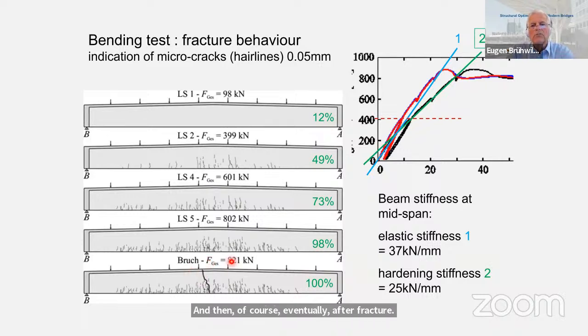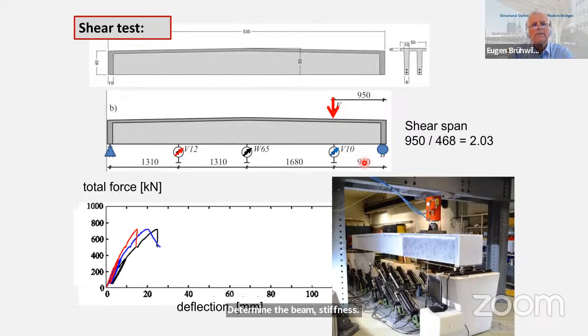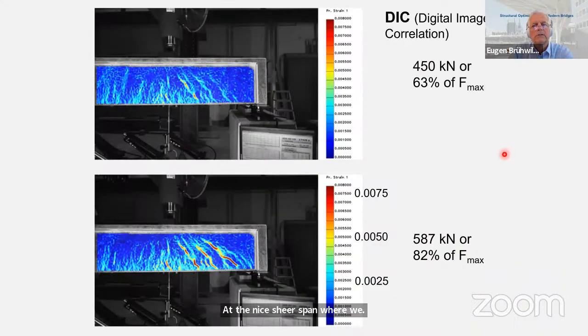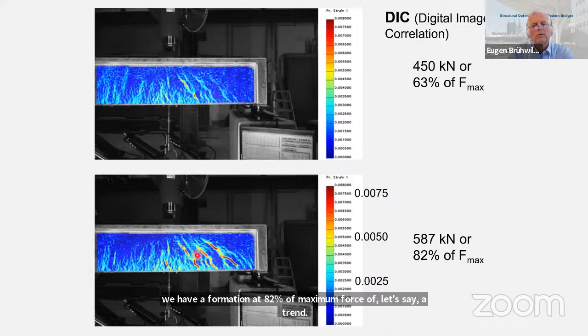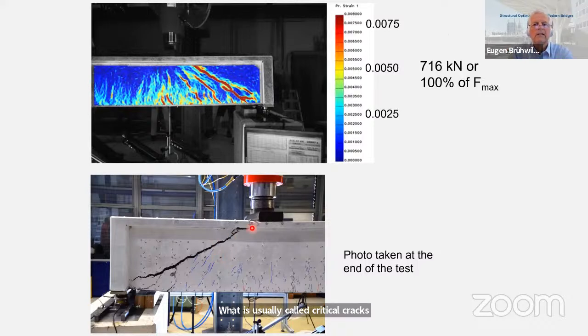These tests allowed us to determine the beam stiffness, which is an important property for elastic behavior. Similarly, the shear test with a single eccentric point load at a nice shear span where we can expect a shear failure. Let's look at the DICs. And we have a formation at 82% of maximum force of, let's say, a trend in order to create what is usually called critical shear cracks. And finally, the fracture occurred here. But we had significant bending, micro crack behavior also at ultimate limit state.